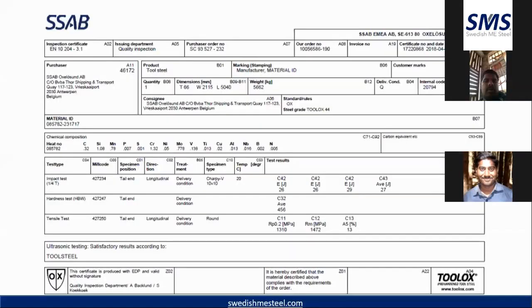This is the test certificate which will accompany all the materials that we give. The Tulux test certificate is different from others in that each and every single plate of the metal is tested. It's not from a block of 50 tons or 100 tons that things are tested. It is an individual plate. For example, this particular one talks about a 66 thick plate, that particular plate of 2 meter by 5 meter. The chemical composition, the hardness value of 45 HRC, the yield strength and the tensile strength, as well as the toughness value is given. And each and every plate is ultrasonically tested, and each has a plate ID. So if you feel that you are not given the proper standard of Tulux, you can always trace back the material.